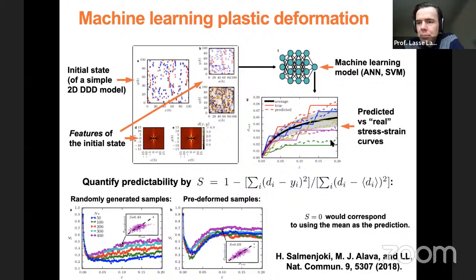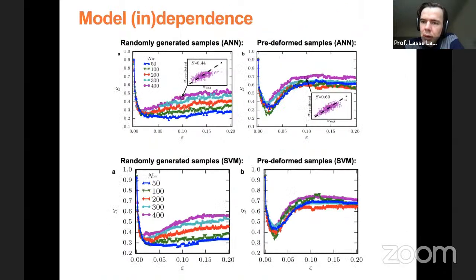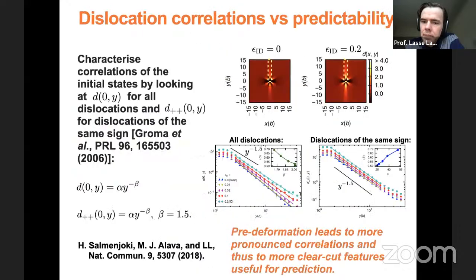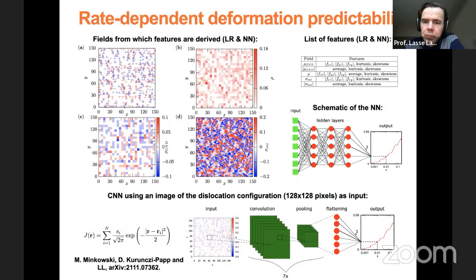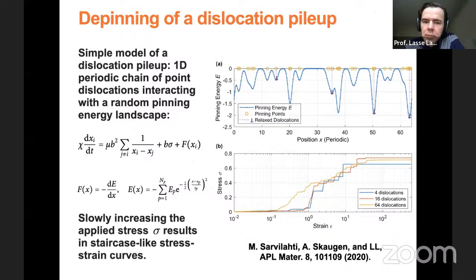Okay. And then at the end, it is a flow, right? At the end, for large strain values, there is a flow, an onset of flow. Yes, in this last model, where you have this depinning transition, you have this kind of one-dimensional dislocation pileup interacting with some quench disorder. If there you increase the stress beyond the critical stress, then you just keep flowing indefinitely.